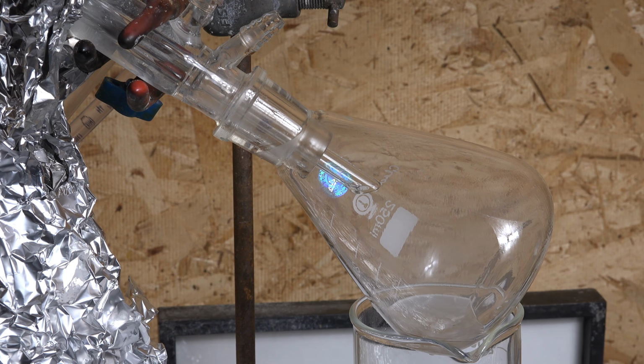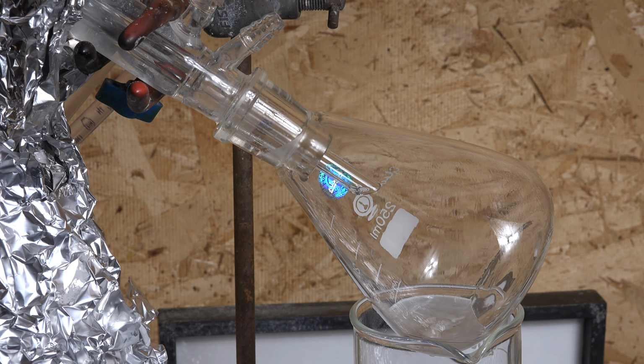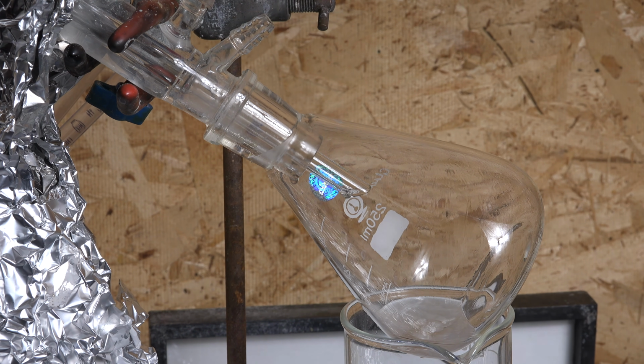The liquid of gamma sulfur trioxide needs some sort of initiator to begin polymerization. Since I melted off the solid plug of sulfur trioxide, I converted all of the polymers into the gamma form and now they can't polymerize again. This would be a good thing to prevent clogging of the condenser, but now without seeing the solid, I don't know if we're distilling sulfur trioxide or if we're distilling sulfuric acid. And looking at the pool at the bottom isn't useful since it solidifies too slowly.